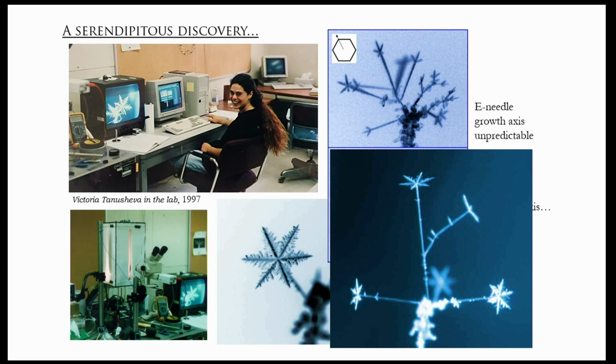And so that's when the light bulb goes off. It's like, oh, the contamination wasn't hurting, it was helping. And so then we played around with different kinds of contamination and found out that acetic acid worked really well. And so all it needed was just a whiff of acetic acid vapor at the right time, and it makes perfect C-axis needles, go figure.